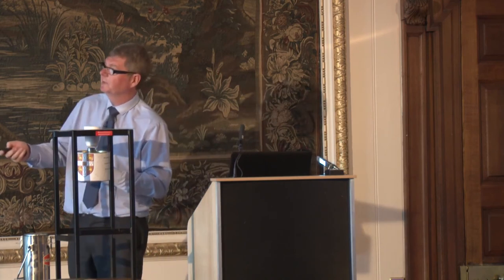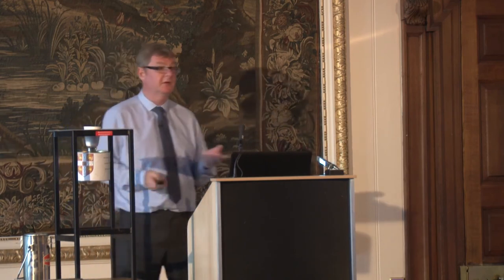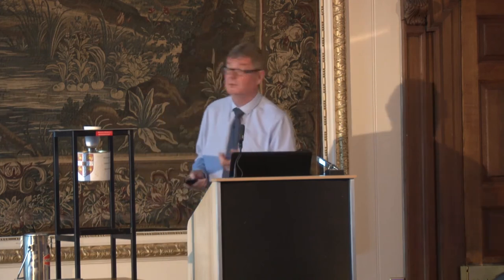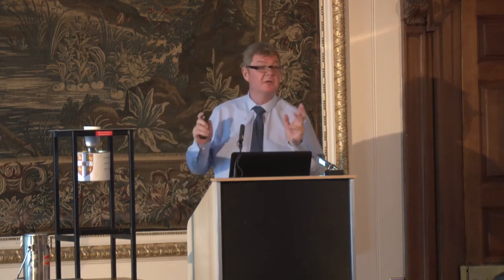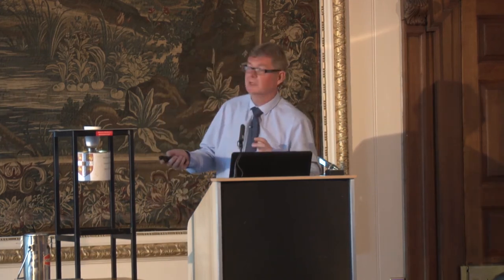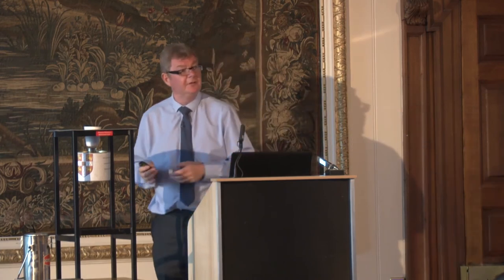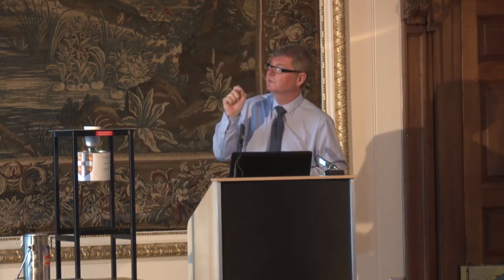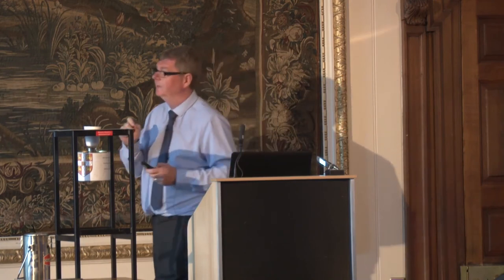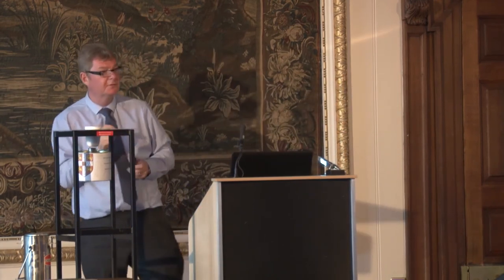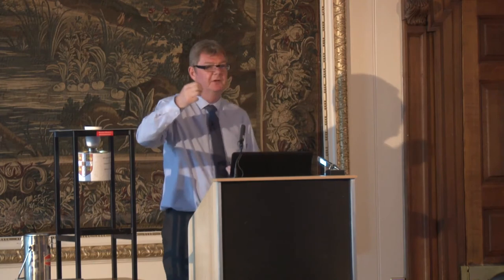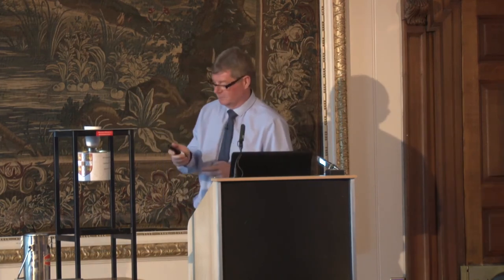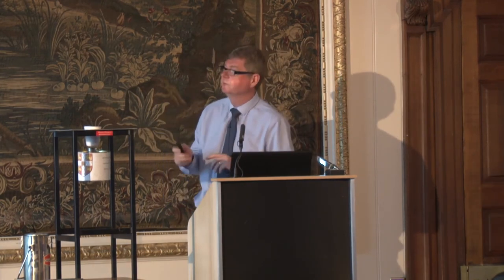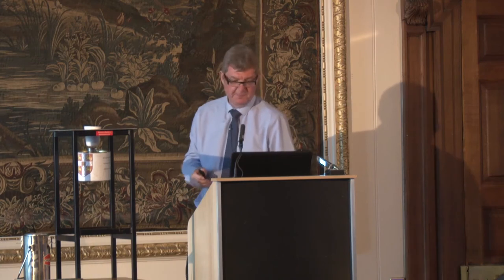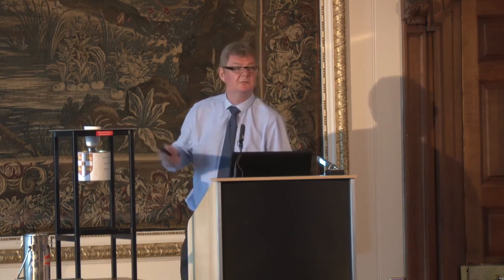The Japanese, when they grow neodymium barium copper oxide, which they grow extremely well, I have to say, and we can't reproduce what they do, but the samples are extraordinarily good, often open a furnace at very high temperature and deliver a seed crystal 1 millimetre by 1 millimetre at the end of a rod which is 1.5 metres long right to the centre of a partially molten material. If you get it right, you get very good results, but it's not really industrially compatible. So now all our seeding is at room temperature.